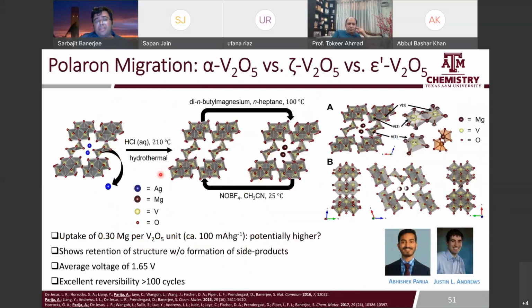So we've had the most success with this structure here, zeta V2O5. We take a silver V2O5 and take the silver out by HCl treatment, or we can also start with copper V2O5, and then this is a chemical magnesiation we've done with N-butyl magnesium. We can stabilize this magnesium structure, and then we even have a powder diffraction pattern with a Rietveld refinement. And what is exciting about this, we can get about 0.3 magnesium per V2O5, 100 milliamp hour per gram.